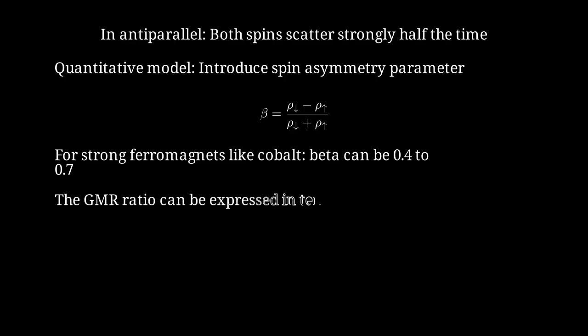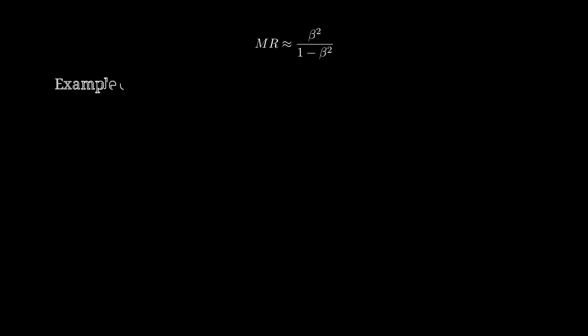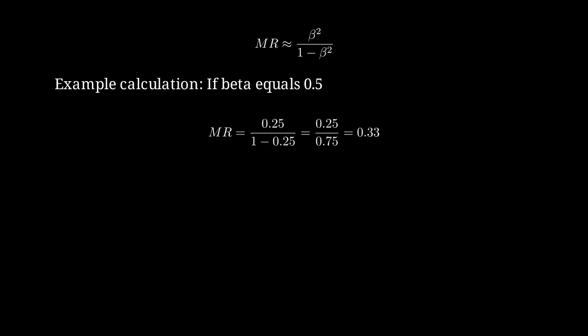The GMR ratio can be expressed in terms of beta through a relatively simple formula in the limit of many layers. MR is approximately beta squared divided by 1 minus beta squared. Let's calculate. If beta equals 0.5, then beta squared is 0.25. MR equals 0.25 divided by 0.75, which equals 0.33 or 33%. This matches experimental observations quite well.